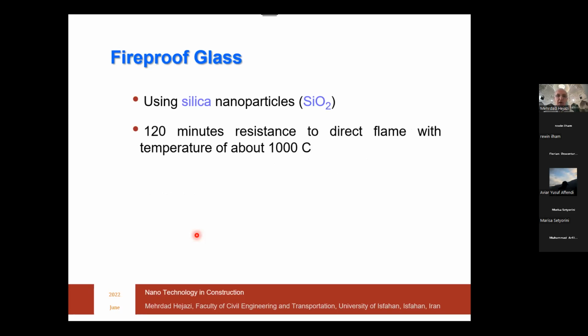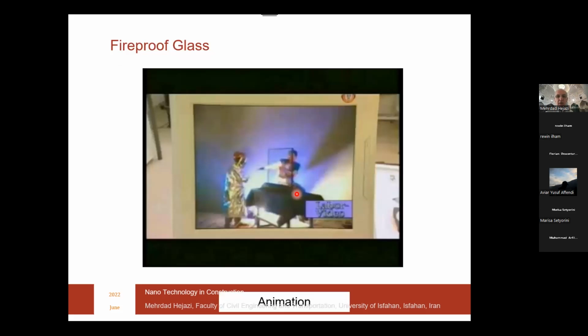Let's go for fireproof glass, which is very important in some cases. I will explain. One solution is use silica nanoparticles in order to make the glass fireproof. And it depends on different standards. In most standards, a fireproof glass must have a minimum of 2 hours resistance to direct flame with a temperature of about 1,000 degrees centigrade, which is too much. It's a very difficult criterion. But by nanoparticles of SiO2, we are able to make such a product. Now I show you. I hope you can see this.